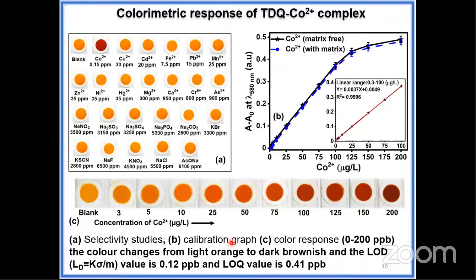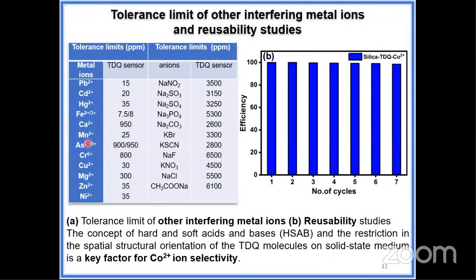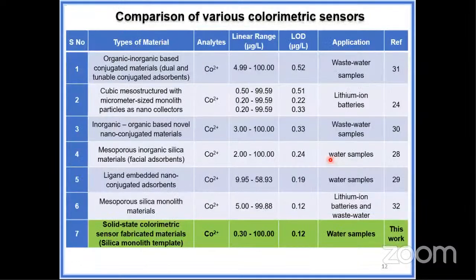Also, we have calculated the limit of detection and limit of quantification for this material by plotting a concentration graph, and the LOD is 0.12 ppb and the LOQ is 0.41 ppb. These are the limits of other cations and anions that we have optimized. Also, the sensor material can still be recycled 7 times without any damage to the original performance. Also, we have compared with other already reported materials. We found that our material shows a superior detection limit.